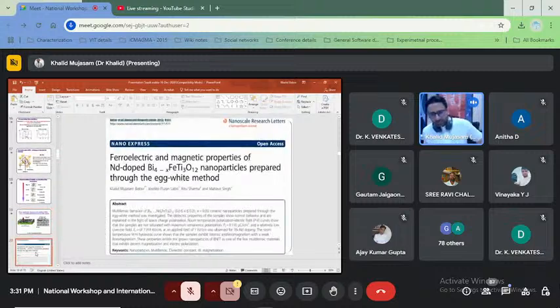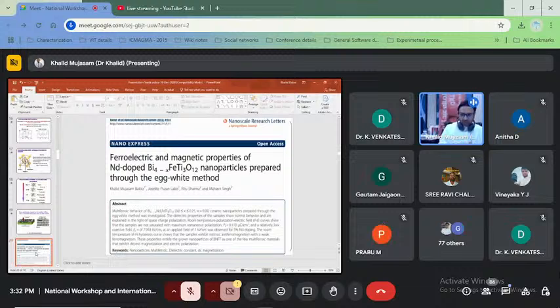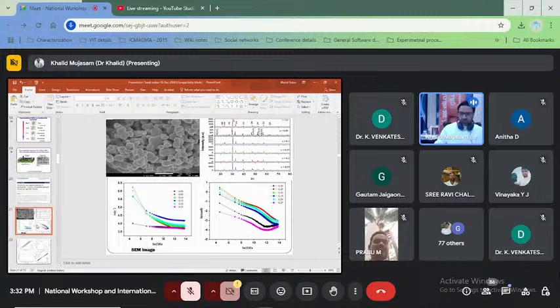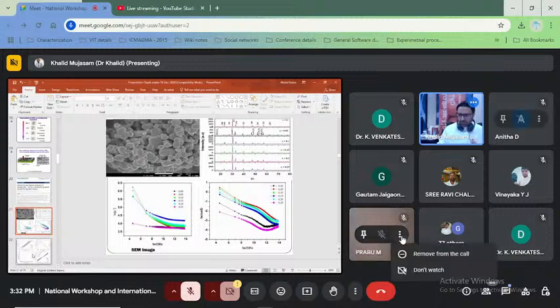So as I mentioned, I will present some of the work which I have done in this spot. We require an S-type structure to determine whether this material can fit into the FRAM application or not. This is one of the earliest works, which was funded by the National Plan for Science and Technology in association with King Abdullah University of Science and Technology. Here we used the bismuth iron-based titanium oxide, and what we achieved from this, going in very shortly, is this structure. It was not a single phase based structure. However, we had some limited dielectric constant and conductivity losses here, which were less than 1.